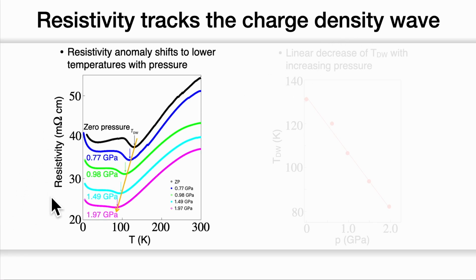So to compare the behavior of spin density wave with charge density wave, here we measure its resistivity. At ambient pressure, a resistivity anomaly happens around 132 Kelvin. Below this temperature, the CDW state appears, and near this temperature, because the CDW disappears and possibly reconstructs the electronic structure, the resistivity drops.